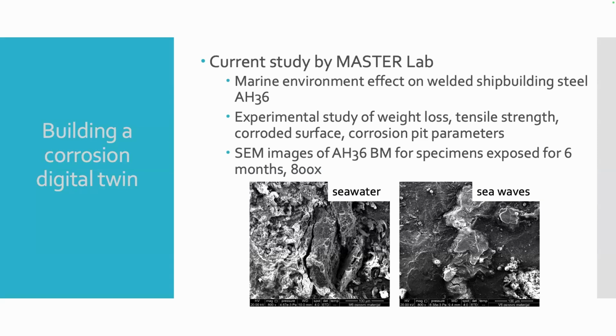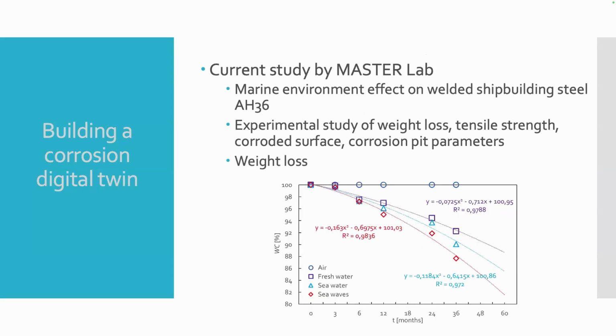Which show the same images of the specimen that was exposed for 6 months to pure seawater, still seawater, under 10 meters deep. And the other one that was exposed to sea waves on the surface of the sea. The main difference is that the edges of the pits are rounded because of this combined effect of the corrosion environment and mechanical loading of the waves.